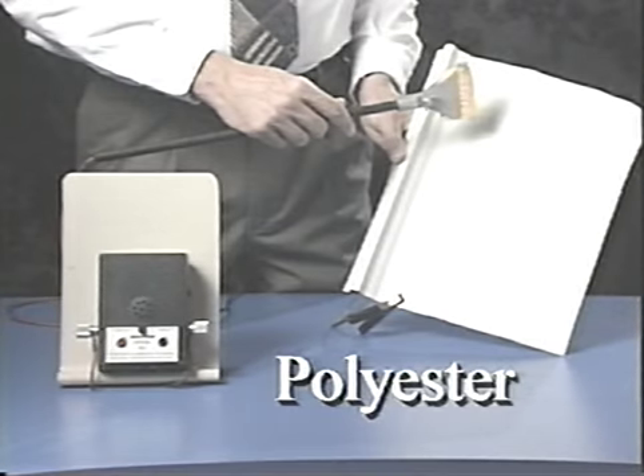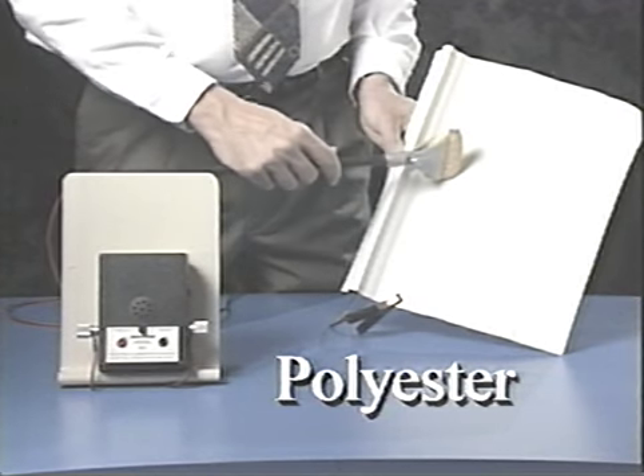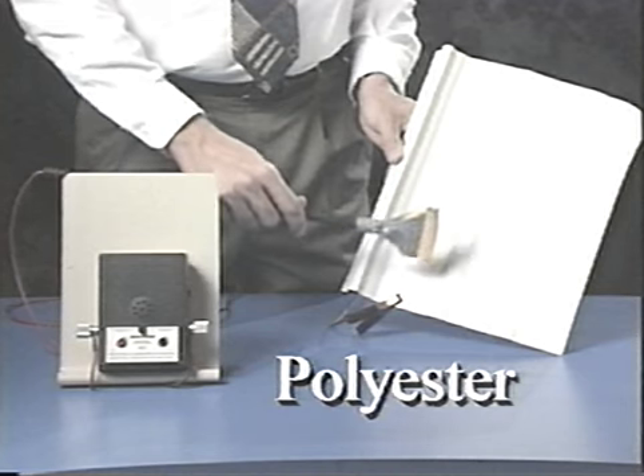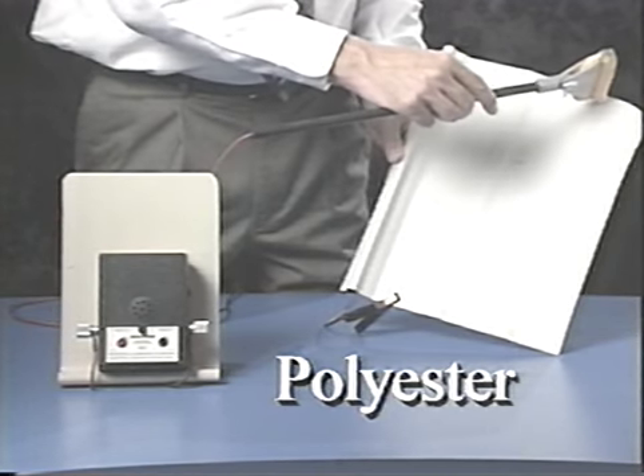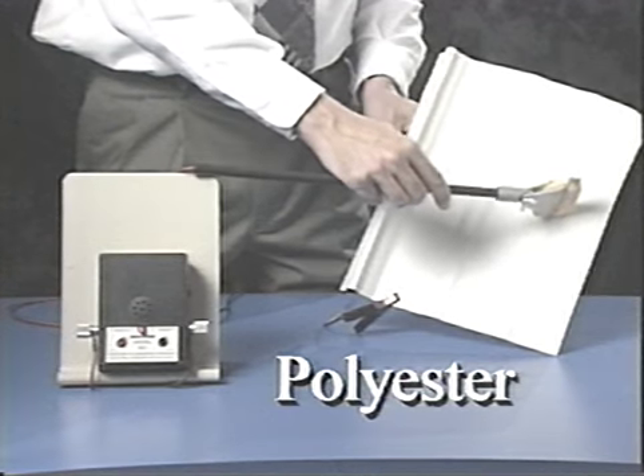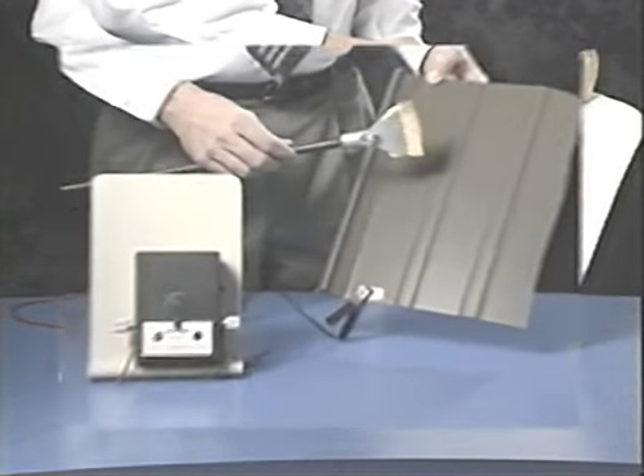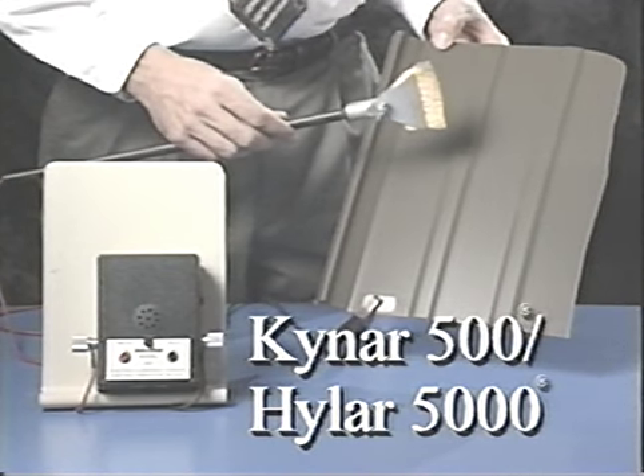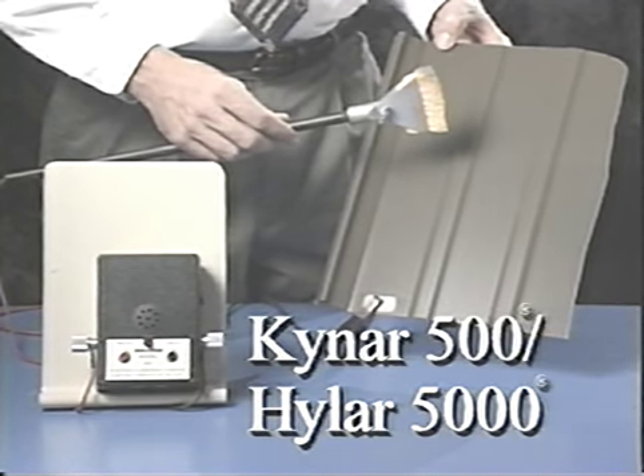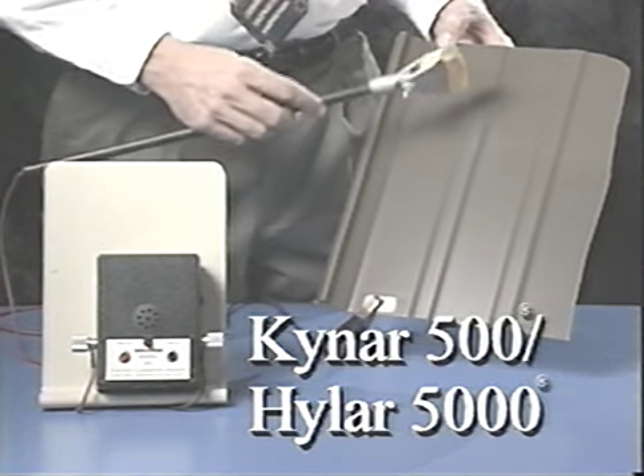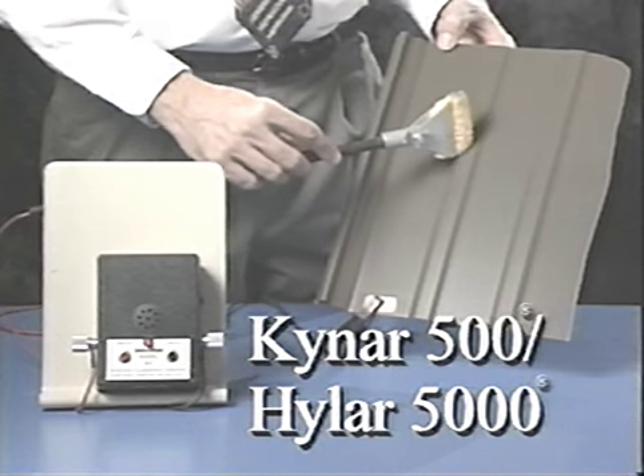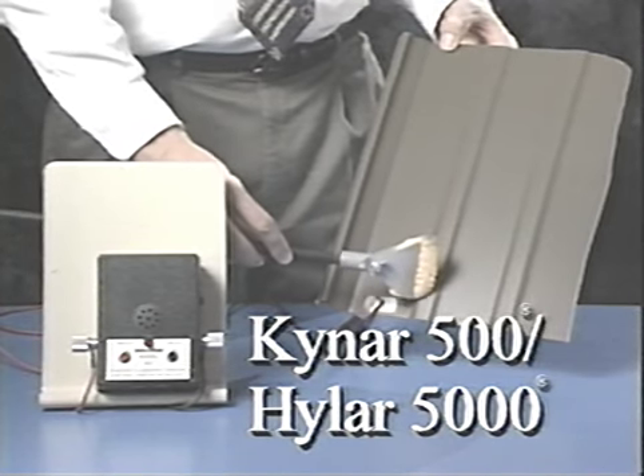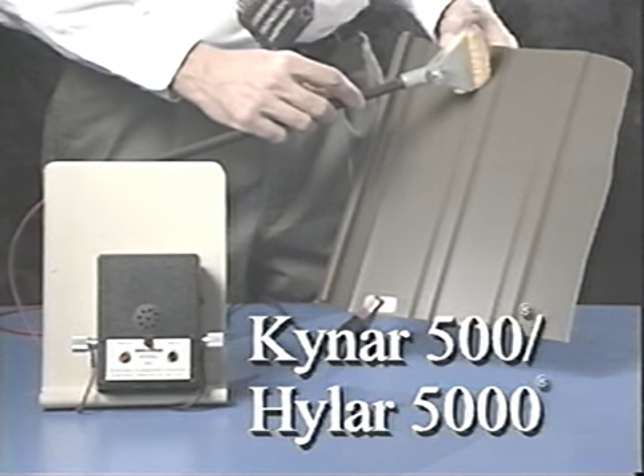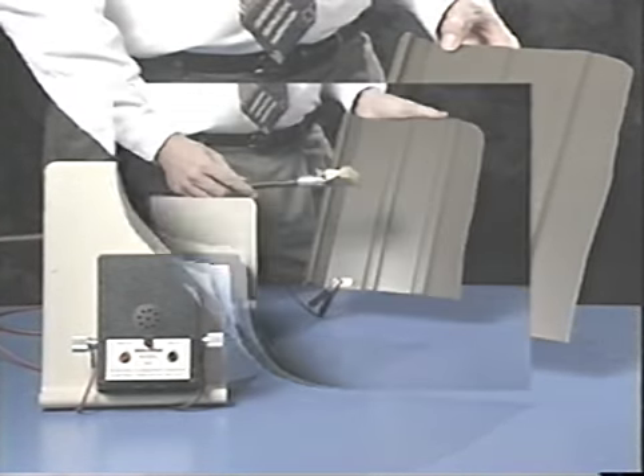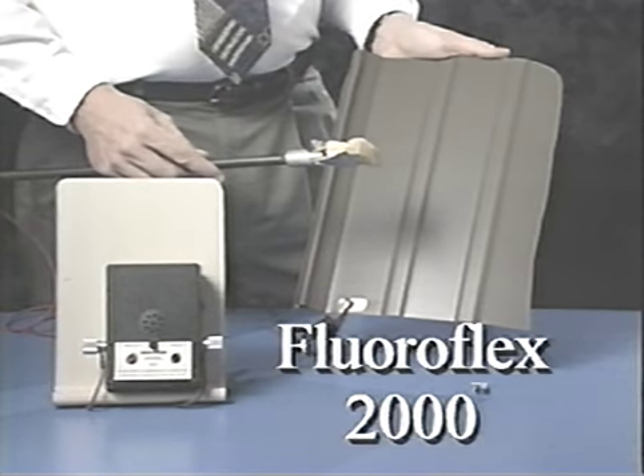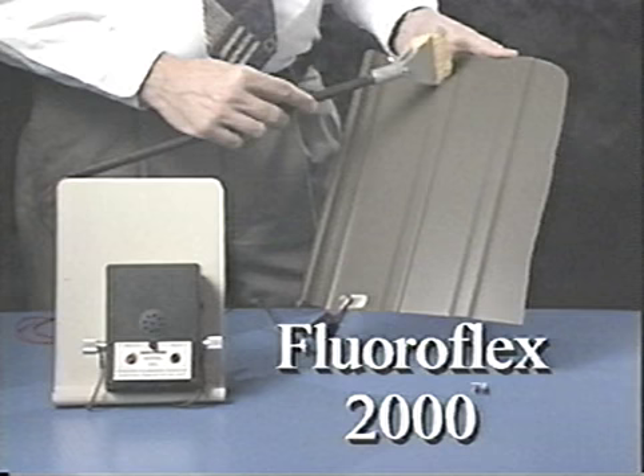This panel was formed from a polyester coating. As you can see, wherever the steel has been formed into a rib, paint film fractures are being detected. So many of them that we get an almost continuous tone. This panel was formed from a conventional 1 mil thick Kynar 500 Hylar 5000 coating. It's more flexible than standard polyester or silicone polyester paints. The fracture detector reveals that there are fewer cracks at the ribs than the polyester coating, but we still find some cracks. We designed Fluoroflex 2000 to be fracture-free at formed areas of the panel.